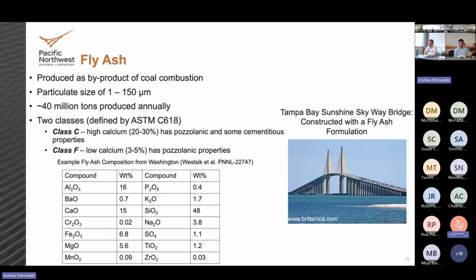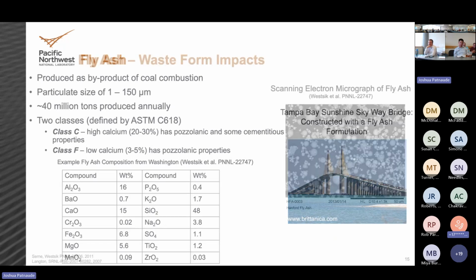So one of the first ones and one of the most widely used supplementary cementitious materials in industrial applications, and one we use in a lot of our waste applications, is fly ash. So this is a byproduct of coal combustion. It's a waste product that just sits in piles at the coal production facilities. It's a fine powder, depending on where you get it from, how fine it is. There's about 40 million tons produced annually. It's used quite heavily, especially in bridge construction or in precast applications of cement. And there's two main classes of it. Class C, which is a fly ash that has high calcium, a key component of doing those hydration reactions. And then Class F, which has low calcium, but usually a little bit cleaner. But again, it's a calcium aluminosilicate material that comes out of a high temperature process. The resulting powder has pozzolanic activity. Go to the next slide.